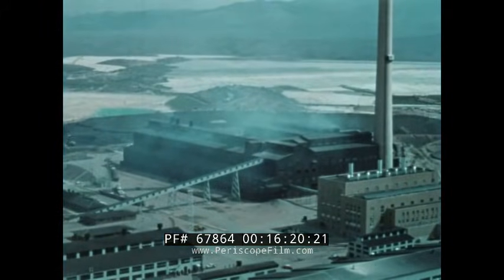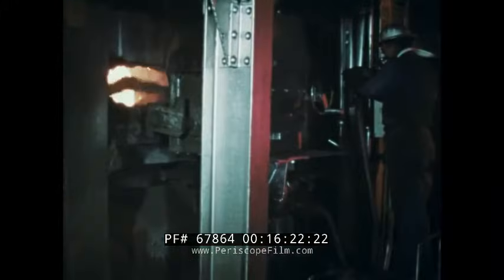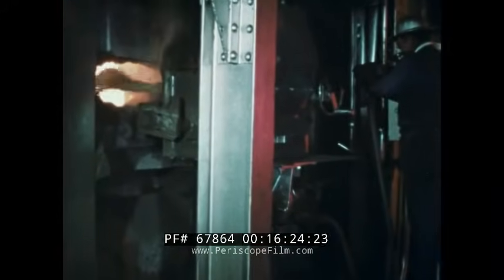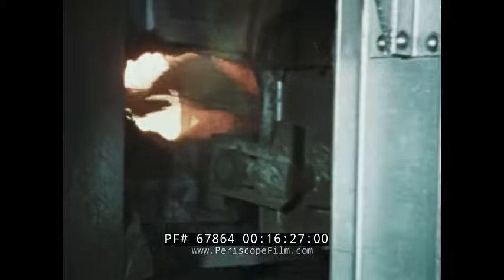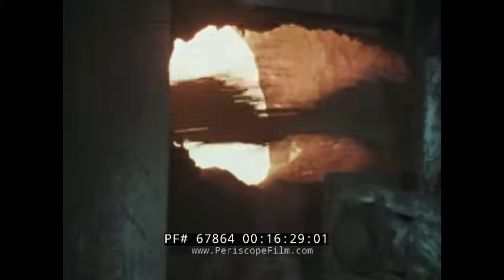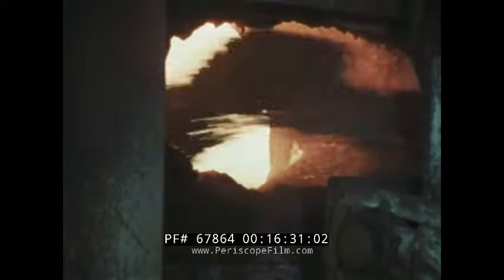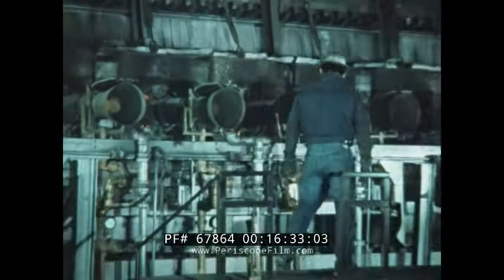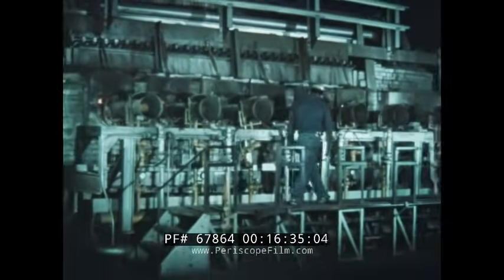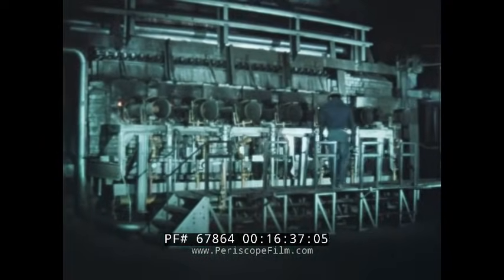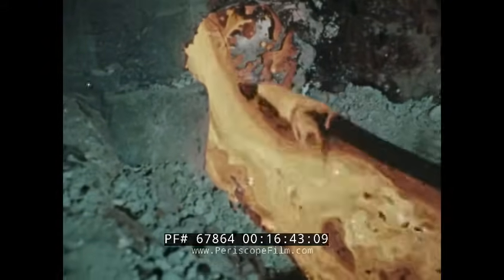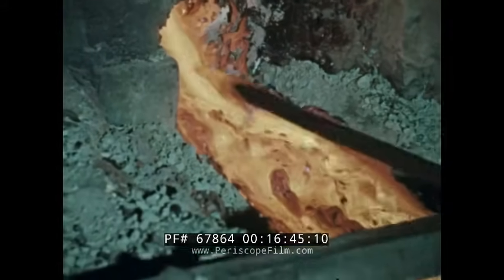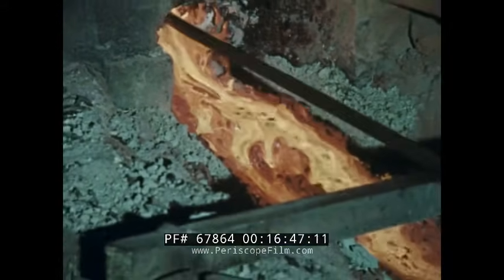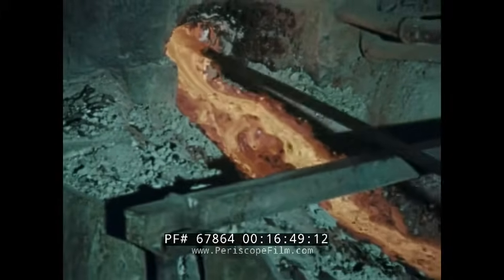In the smelter, the concentrate is charged into the reverberatory furnace. At nearly 3,000 degrees, it is reduced to a molten pool. Some of the iron floats to the top as slag, and the mat containing copper, sulfur, and the remaining iron settles to the bottom. Periodically, the slag is withdrawn from the reverberatory furnace and discarded.